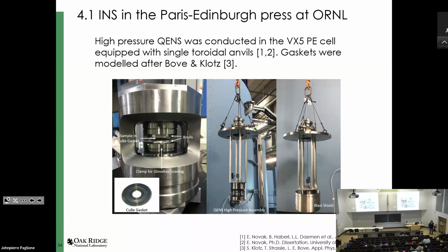Most neutron beamlines, unlike a synchrotron beamline, you don't walk up to. They're actually down in tanks so that things can be evacuated and you can reduce backgrounds. Additionally, these cells can blow out, which can be quite violent. So we added a blast shield, which actually is a modified pot. Really, this was a pot from McMaster. So these are all things that can be optimized because obviously they contribute to background.